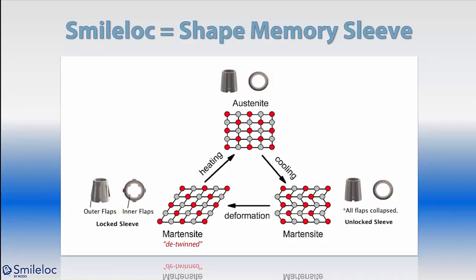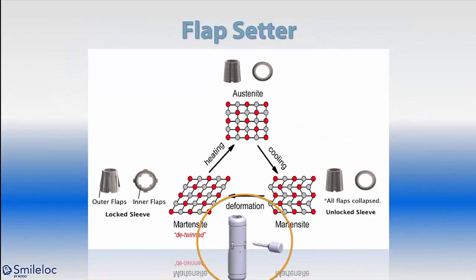So Smileloc is memory metal that can be distorted. So you can see when it's in the austenite form, everything is smooth. When the Smileloc sleeve is cooled, the metal changes to a lattice pattern that can be mechanically deformed to actively engage the undercuts in the RODO abutment and the coping. We have to bend the inner arms and the outer arms on the Smileloc in order to retain the crown on the abutment. Deformation is achieved through the Smileloc arm setter, as we will show you here.